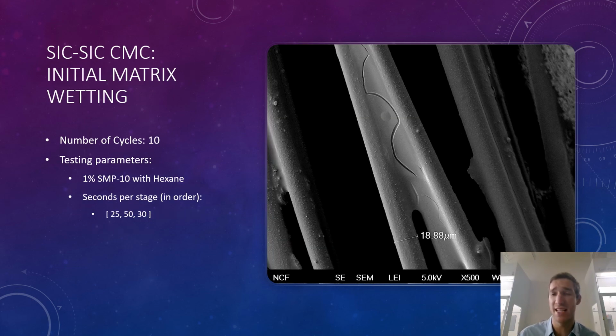Moving on from 5 cycles, we can see 10 cycles. Here we can see a more significant buildup of interstitial matrix between fibers. We do have cracking. As you can see, a large crack coming down the middle. This isn't a major issue at this point because many of the cracks, as they form initially in the cycles, are actually re-infiltrated by subsequent infiltrations, and they actually get filled up. So even if you have a large crack, this crack is about 1.4 microns in width, this actually will be re-infiltrated. The polymer will seep into this as it is re-infiltrated and fill up the crack as it builds everywhere else as well. So this was 10 cycles, again with the 1% SMP10 and the same robotic system parameters.